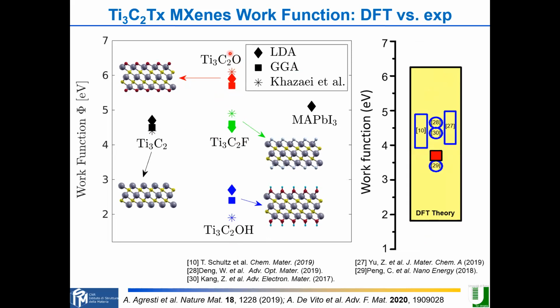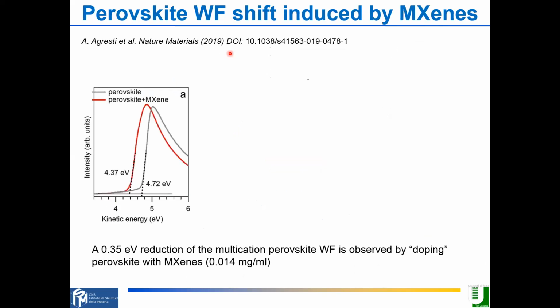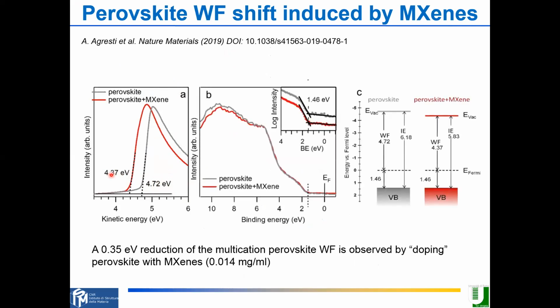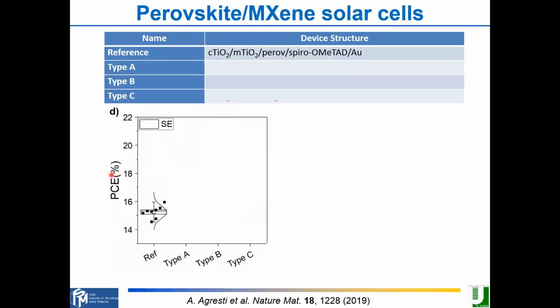For everyone who is doing devices, this is a fantastic wonder material because you can tune the work function. So what we were trying to do is use this material to change the work function of the materials forming the perovskite solar cell, in particular the perovskite or the other materials. For example, you can see here this UPS measurement. You can shift the work function from 4.72 electron volts without MXene to 4.37 with MXene. So we can tune the work function. Let me make the story short: you can change the band alignment between the layers and the perovskite. And this was the effect.